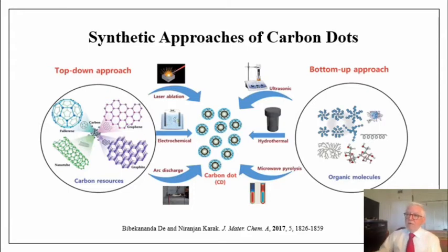The second approach is the bottom-up approach. That means we start with small molecules, and we will see in the next slide the way to produce these carbon dots. The main procedures use ultrasonic, hydrothermal, and microwave pyrolysis. But I must say that if we look at the number of papers published, the hydrothermal approach is quite important, maybe 85% of the papers published for the bottom-up approach.